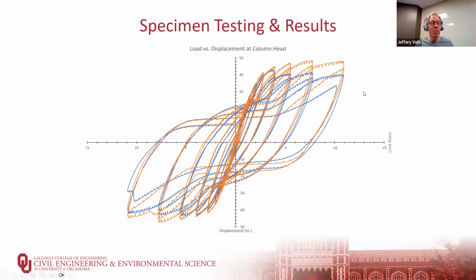So again, the important thing is to recognize that the only difference between these two specimens is the core concrete. The UHPC apparently provided more capacity, perhaps more buckling resistance to the steel tube, because the longer you can go before that steel tube buckles, if you can fully yield that cross section, reach the plastic moment capacity of that steel tube, you're optimizing that material. It can't get any better than that. That's the ultimate goal. If it buckles, you're not using the material as efficiently.